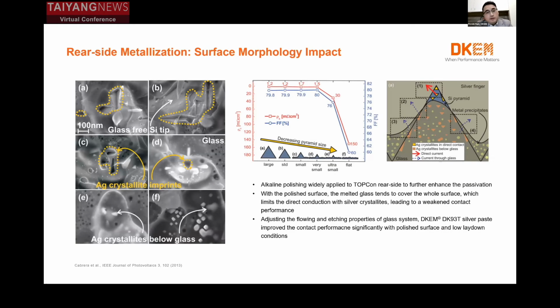The first one is the morphology impact. Right now in industry practice, alkaline polishing is widely applied to the TOPCon rear side to further enhance the passivation. But it brings a bad thing: the contact becomes very poor and EL issues happen. So what's the reason behind this, and how can we deal with it with paste? With the polished surface, the melted glass tends to cover the whole surface, which limits the direct conduction with silver crystallites. This gives a weakened contact performance.